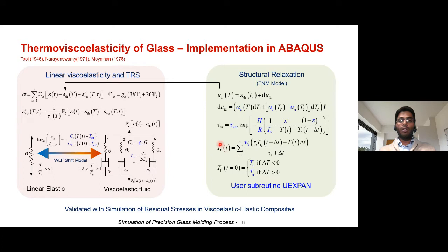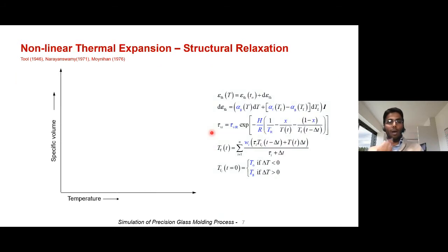Here we evaluate a temperature called the fictive temperature. This quantity is not a physical quantity, but an artificial temperature which is present in the glass. If you are able to compute this artificial temperature, you would be able to capture the nonlinear expansion behavior of the glass. Without getting into the mathematical details, I would like to explain what is physically happening there, where the nonlinear expansion actually comes from.